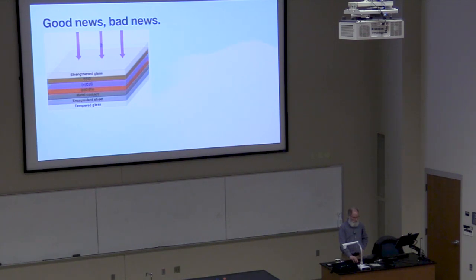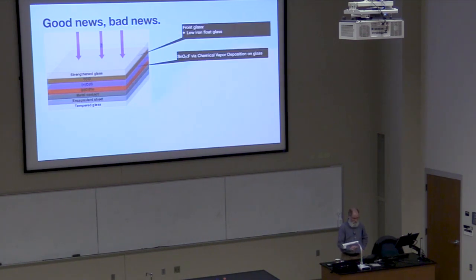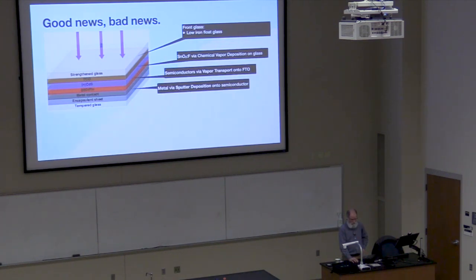So the end of that story is good news, bad news. You look at this solar cell device: we make the glass, we coat it with tin oxide, but we can't make cadmium telluride or even good quality amorphous silicon by our process. So that's where the solar manufacturer comes in. They make the semiconductors. We can't make good metals either, so that's by a different process.